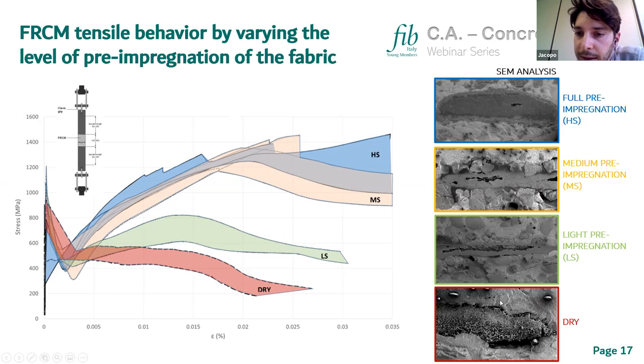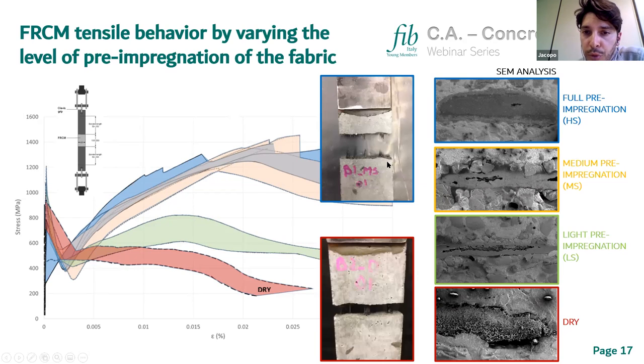Here you can see the same of the section. In the case of dry yarns, we have a very bad interface between the dry filaments and the mortar, while for the fully pre-impregnated yarn, we have a higher quality of the interface, which allows us to reach this behavior with higher tensile load. And these are the failure modes. In the case of dry yarns, we have the slippage of the internal filaments within the mortar, while in the case of coated yarn, this is the fully pre-impregnated yarn, we reach failure due to breakage of the internal reinforcement.